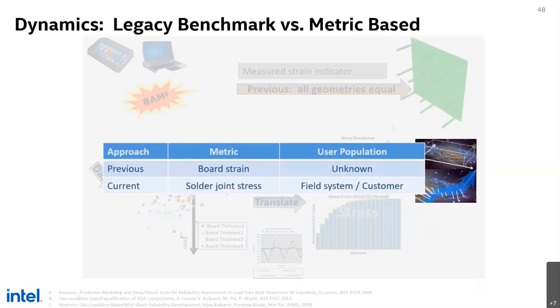So previously, we would have just measured board strain and made sure all the components stay below board strain. But it turns out that board strain by itself, because you can measure it, one is there's variation to the measurement, and the other one is variation in the systems that it goes into. It's kind of useless as a metric. The best thing to do is measure the stress, and then you can understand how people are doing their designs to manage that stress. And that's what we've done here.